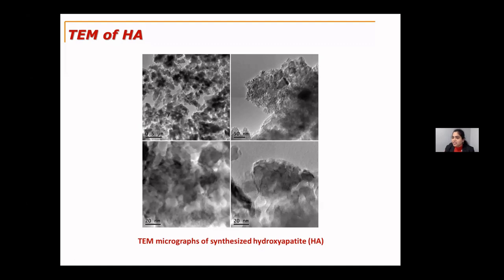So the particles are still in irregular shape because they went through the nanomill and then we ground it by hand, using the mortar and pestle. However, under the 20 nanometer scale, we can see slightly the hexagonal planes for these hydroxyapatite particles.